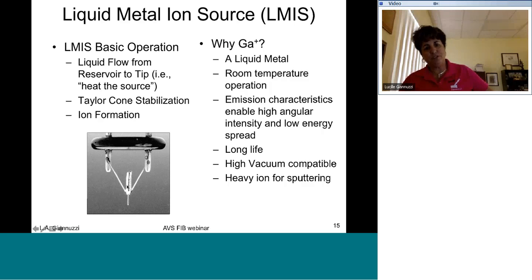Yeah, so what happens is a little blob of gallium, the liquid metal, just flows down the tip, and you want a little tiny blob of gallium. And then you throw a high voltage across there, and that generates a so-called Taylor cone. The Taylor cone stabilizes, and then you get ions from it, and I'll show you a little bit more about that too. And because gallium can remain supercooled, you don't have to keep it heated. You heat it once, and it will stay working as long as you're using the gallium until this little blob is depleted. So it can work for a week or more before you have to heat it again.